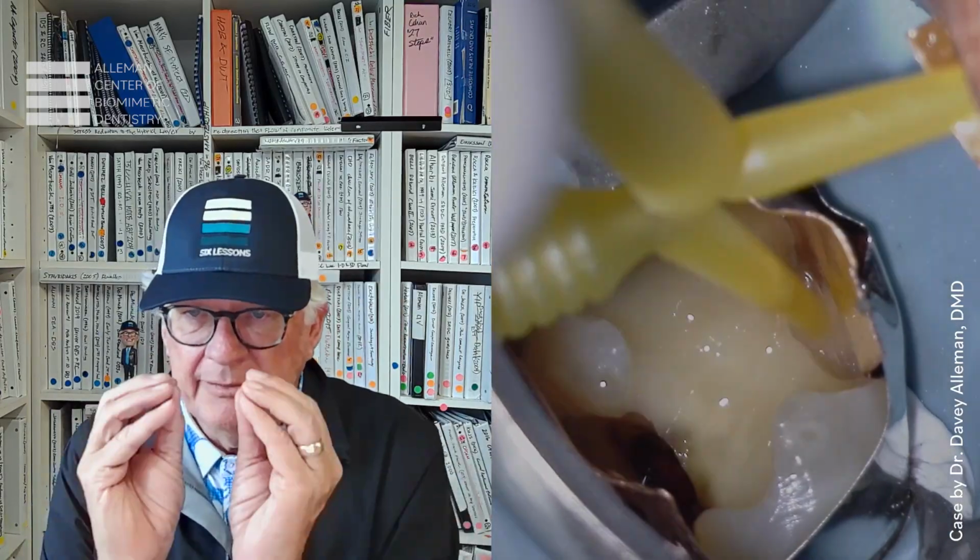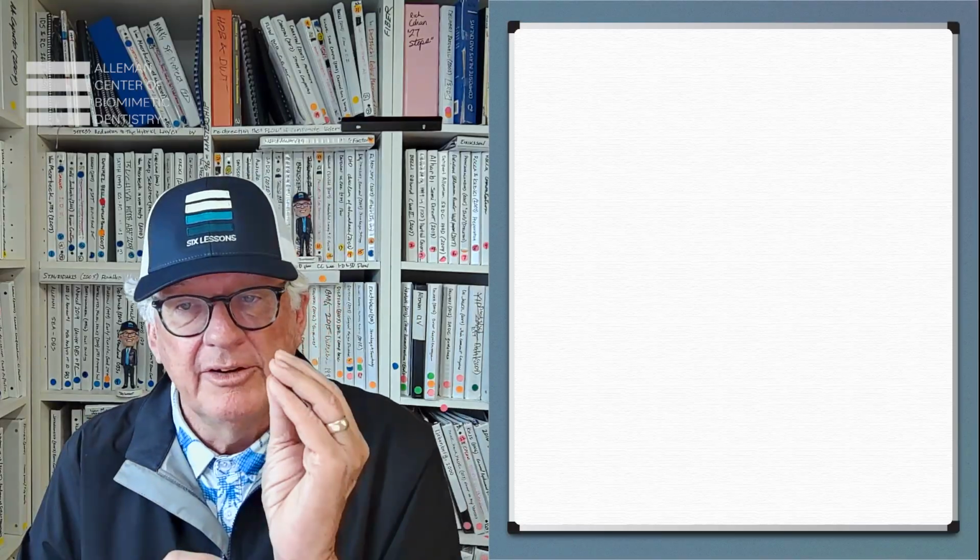And so dental bonding agents have two important differences. Each dental bonding agent has a primer and an adhesive. And if you separate those bonding agents, it's much better. If you mix them together, and that's called a simplified bonding agent, then it's a little bit faster. You gain about 30 seconds, maybe a minute, but you may lose 10 years of bonding performance by using those simplified agents. So we don't recommend the simplified agents. All of the gold standard agents have this separation of primers first, and then adhesives second.